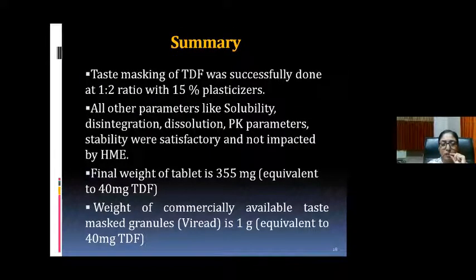So in summary, the taste masking of TDF is successfully done at the 1:2 ratio with 15% plasticizer, and all the other parameters like solubility, disintegration, dissolution, and the PK parameters were satisfactory and not impacted by the HME. Even the final weight of the tablet is 355 mg, which is equivalent to 40 mg of TDF, whereas the weight of the commercially available taste-masked granules, Viread, is 1 gram for the equivalent of 40 mg TDF. So this will be the best application for future study.